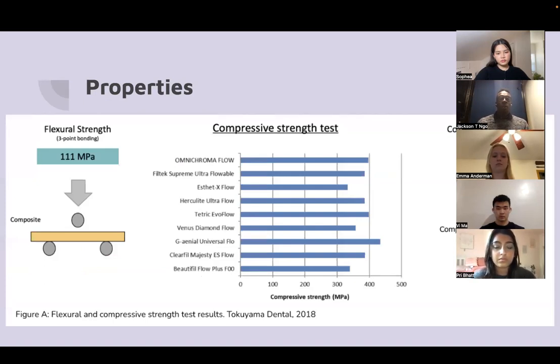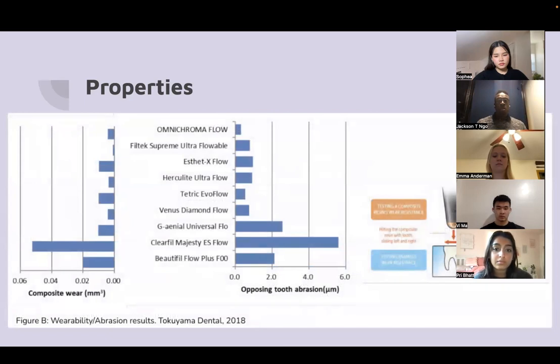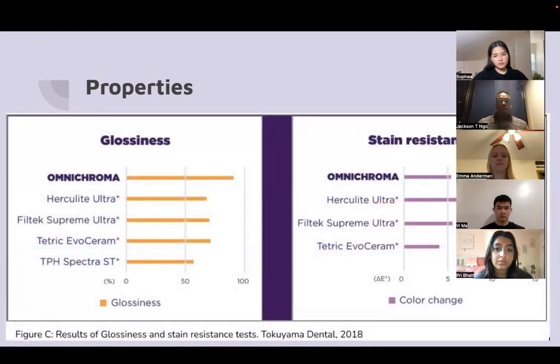The compressive strength of about 400 megapascals and the flexural strength of 111 megapascals are at levels higher than the average among commercially available resin composites. In terms of hardness and wearability, Omnichroma is hard enough to withstand the forces of mastication while still retaining polishability. In a test of 50,000 cycles, Omnichroma exhibited an excellent balance of not being worn down while also not wearing down the opposing enamel. In polishability tests, the product was seen to have high levels of glossiness. In stain resistance, the composite resin had a relatively low extent of staining and so will resist staining for the life of the restoration.